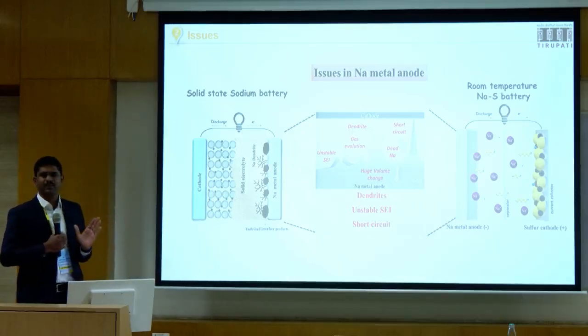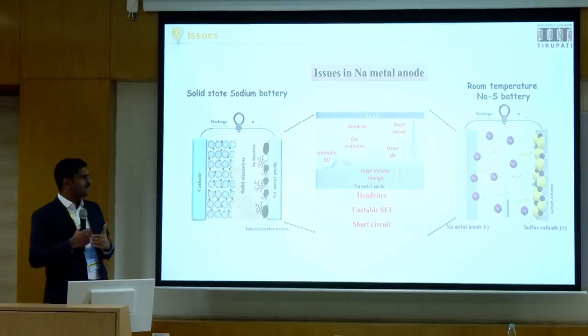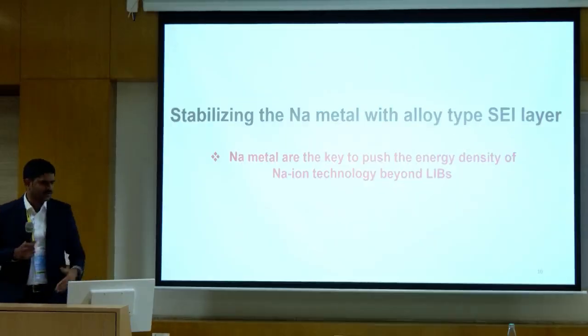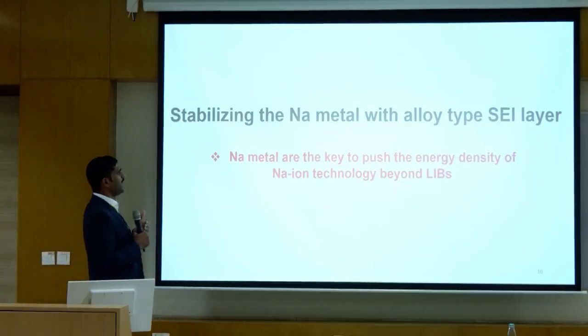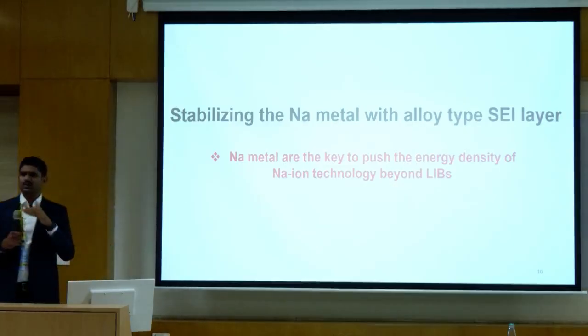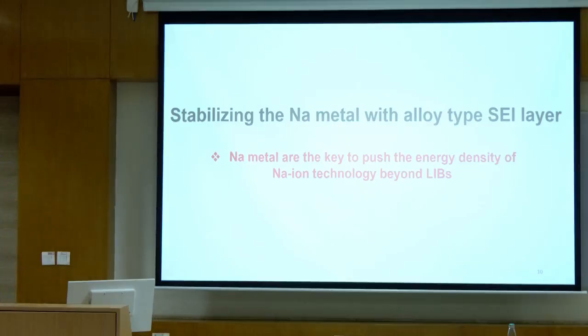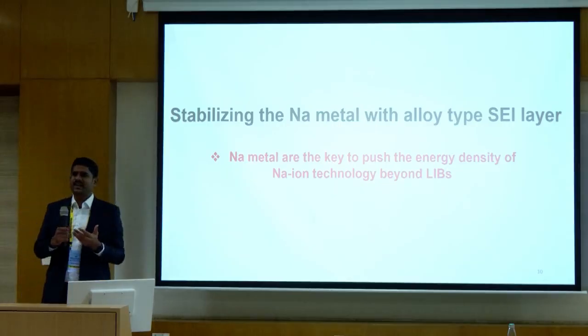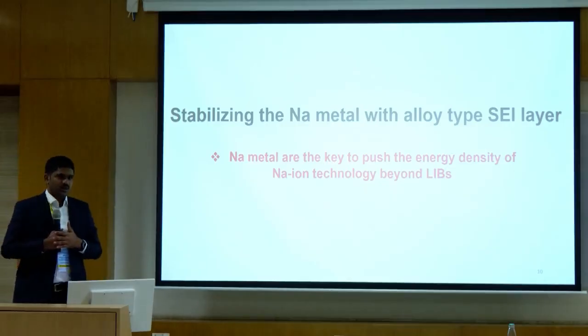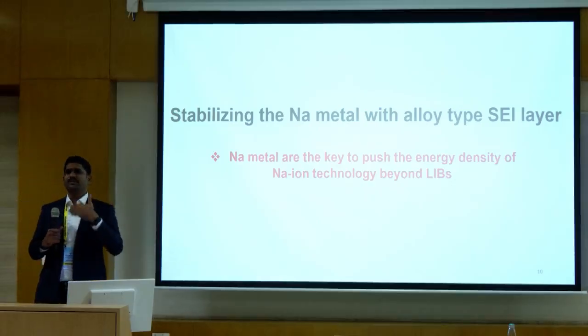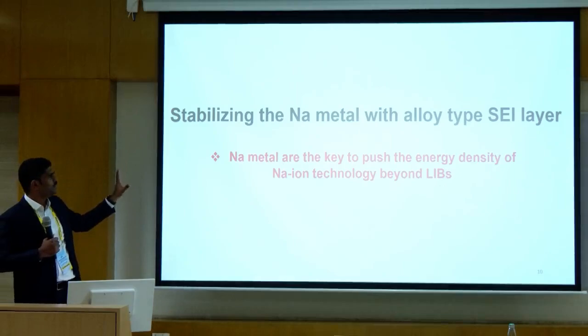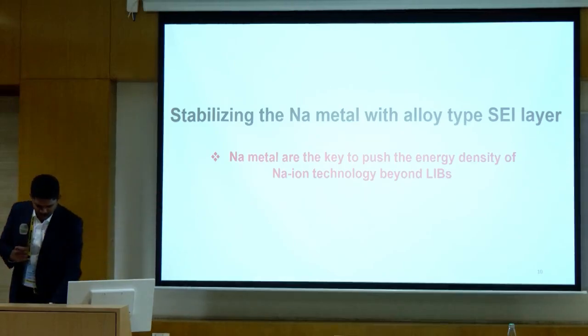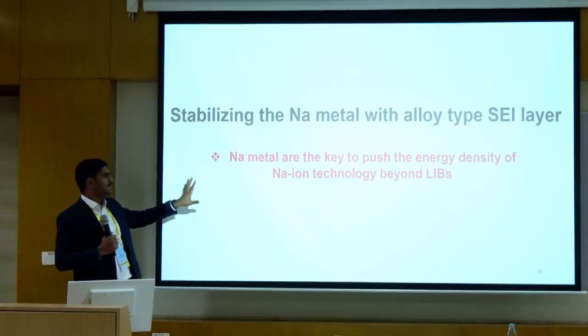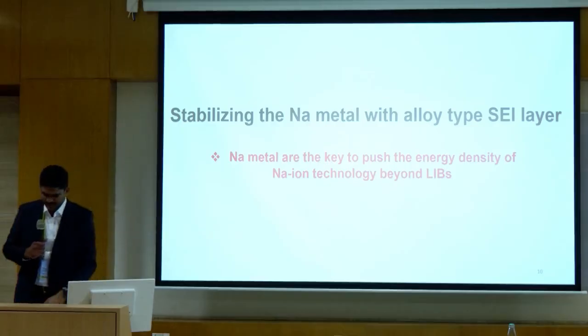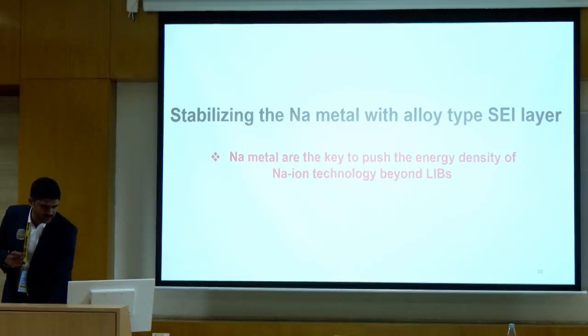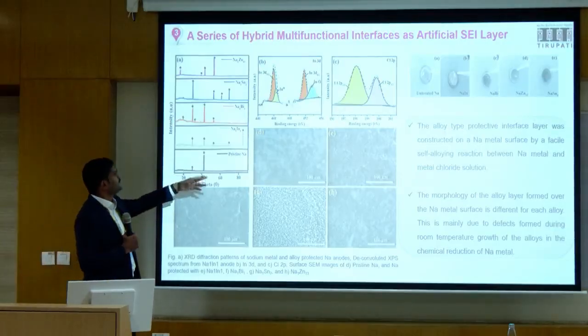Why these dendrites are happening is due to poor interface stability between the electrolyte and metal. So our research group has tried to stabilize the sodium metal by developing sodium ion conducting alloy layers over the sodium metal. So rather than letting the SEI layer form naturally over the sodium metal, we have grown it artificially over the sodium metal. The first thing is we try to stabilize the sodium metal by developing an alloy layer. We realized that this will really push the energy density of state-of-the-art sodium-ion battery technology beyond lithium-ion battery technology. So we have developed a series of alloys.